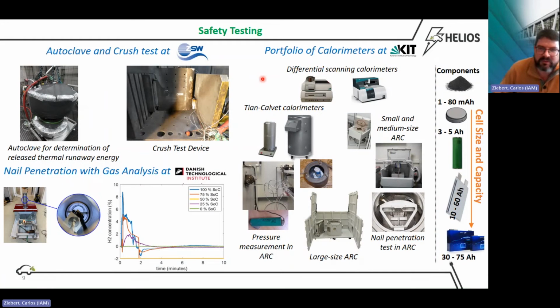For the safety testing, we have a whole portfolio of calorimeters at my institute, so we can investigate from component level up to 75 ampere-hour cells in our different calorimeters, and there we are doing safety tests. For example, one interesting finding was that when investigating thermal runaway experiments in the calorimeter with cells without this fixture, the cells went to thermal runaway 20, 30 degrees earlier.